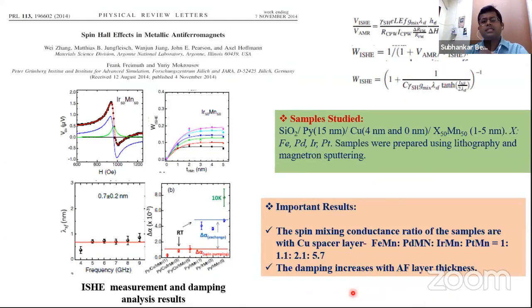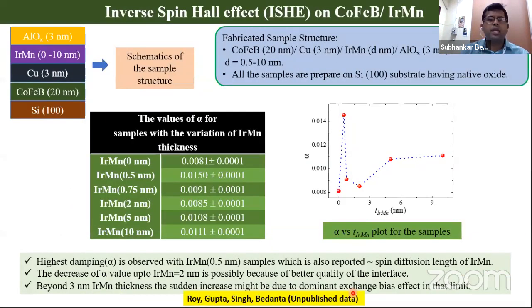Okay, so this is another compound, iridium manganese, which has already been studied by the group of Axel Hoffmann. They studied it with permalloy, but we try to focus on this interesting ferromagnetic material, cobalt iron boron, with iridium manganese. But we put a special layer of copper so that you don't have direct exchange coupling, so that there is no exchange bias. And copper has a high spin diffusion length, so you can still interact and pump spins basically from the ferromagnet to the antiferromagnet.